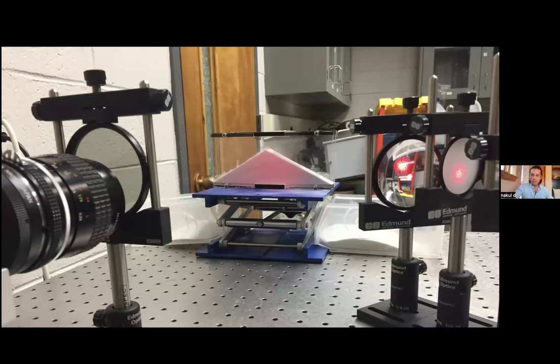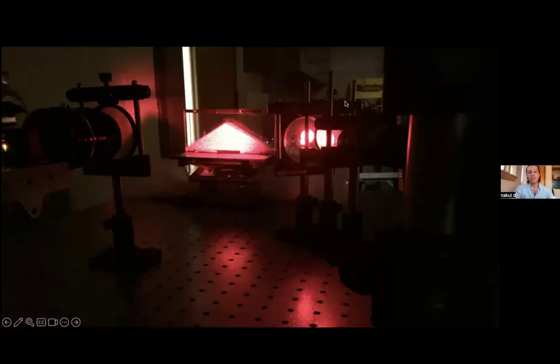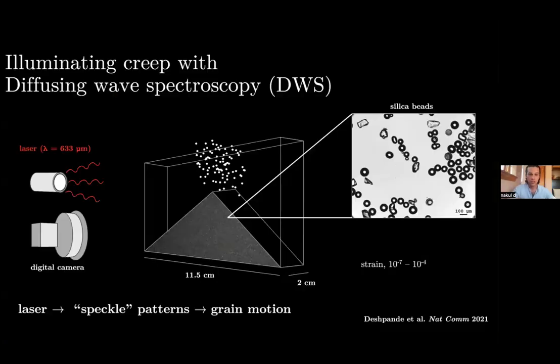So this is a picture of the experimental setup that I'm going to be talking to you about today, which provides the backbone for all of the observations that I'm going to show you. It's called diffusing wave spectroscopy, okay? The setup is humble enough and looks real cool when you turn off the lights. The idea is that we use this laser light to illuminate the sand pile and make observations that allow us to measure creep, okay? In our system, it's a little acrylic box with these dimensions. The grains that we pour into the system are silica beads. Most of them are spherical, but there are some impurities of glass and so on. And the diameter of these grains is about 100 microns.